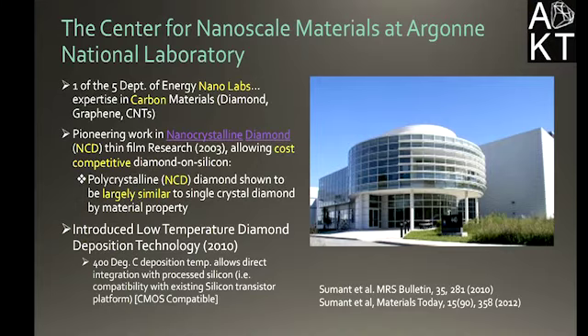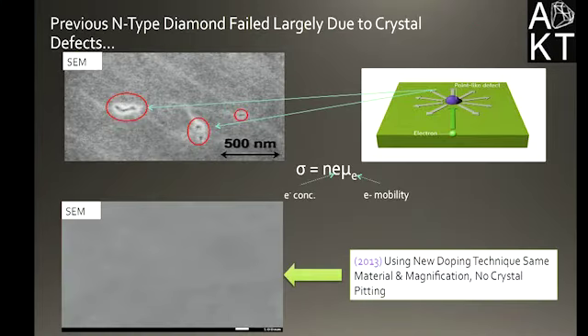So if we fast forward a few years later, CNM actually introduced in 2010 a low temperature diamond deposition method, where now we can deposit diamond at 400 degrees C. Which was a breakthrough. So the main problem, N-type doping, remained.